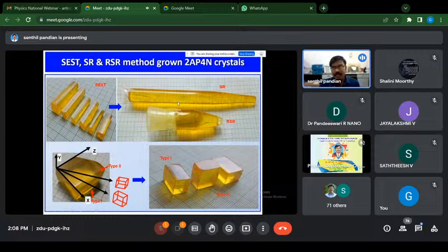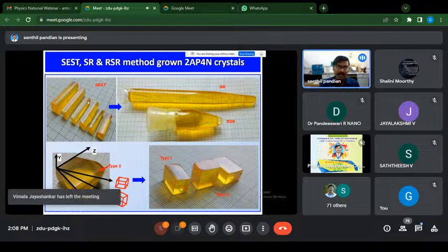So in order to avoid this issue in the SR method, we have made several slits, which means holes, on this SR glass sample. We have completely rotated this RSR method with the solution, seed crystal, everything rotated. When we rotate this solution with crystal, the impurities are pushed out from this SR glass sample. So compared to the SR method grown crystal, one can avoid or minimize the impurity segregation in this RSR method grown crystal. So naturally, the physical properties of these RSR method grown crystals are very high compared to the SR and conventional method grown crystals.